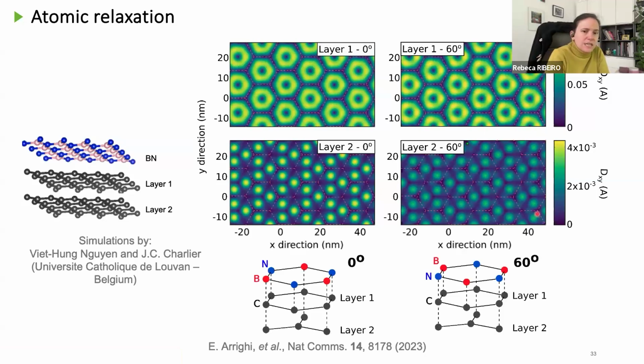The origin of this difference is that if we look at what's happening at 0 and 60 degrees in the commensurate state, where graphene is already stretched to match the layer of boron nitride, we can see that, in fact, for the second layer, the one that is far, in one case we'll see only boron atoms, and in the other case we only see nitrogen atoms. And we are just talking about van der Waals forces. So nitrogen and boron will not have the same effects on carbon, even if it's a second layer. And that's why the displacement of the atoms in the plane will be stronger in one of the cases and weaker in the other case.